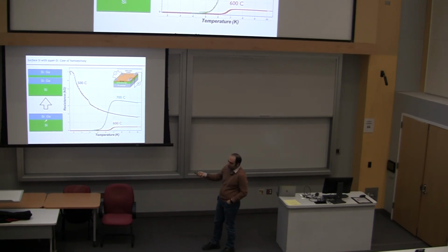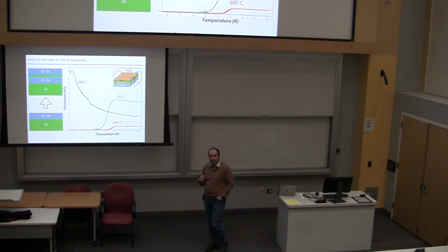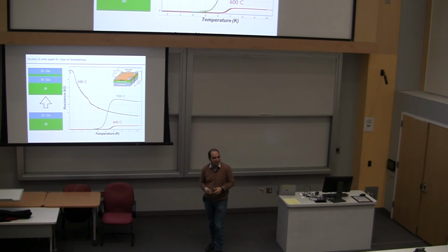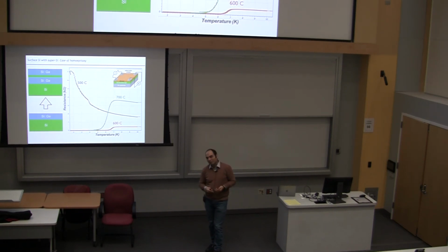So in this one, we have silicon. We grow silicon germanium doped, and then we anneal it. And this is resistance as a function of temperature. For some annealing, we actually get no superconductivity. For annealing at about 760 degrees, we get a TC of about 6 Kelvin, right? Gallium superconducts at 1 Kelvin. Silicon obviously doesn't superconduct. So this is a new superconductor with 6 Kelvin superconductivity. We can debate what kind of superconductor it is.